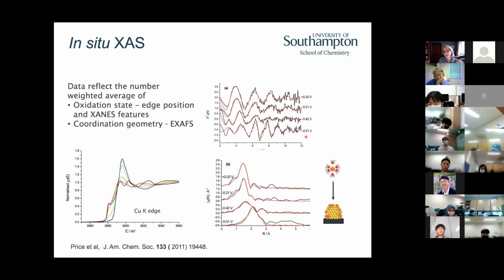Then when I start to put the copper on the gold, what happens is the period of my oscillations decreases. So my distances are longer than the metal distances, but the damping goes away. So I see the oscillations are sustained out to higher K. And that's telling me that the atom that the photoelectron is bouncing off of is heavier. So you can see this in the raw data.